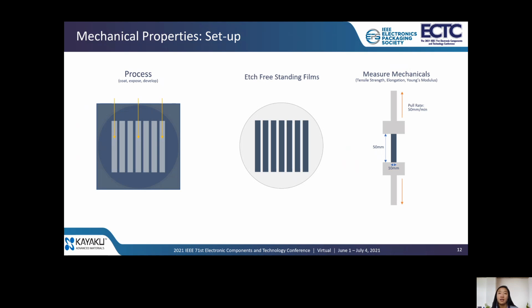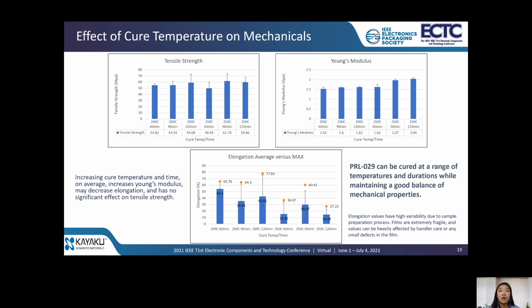Any slight misalignment onto the Instron or any defect in the film will lead to permanent break or premature break. So with that, let's take a look at some of the new data we've generated regarding the effect of cure temperature and time on mechanical properties. We know that customers using dielectric materials may have their own methods of curing due to pre-existing process requirements. Here we have tested different cure temperatures for PRL 29 at 200 degrees C and 250 degrees C, and then different durations at 60 minutes, 90 minutes, and 120 minutes. Then we measured the mechanical properties for each cure.